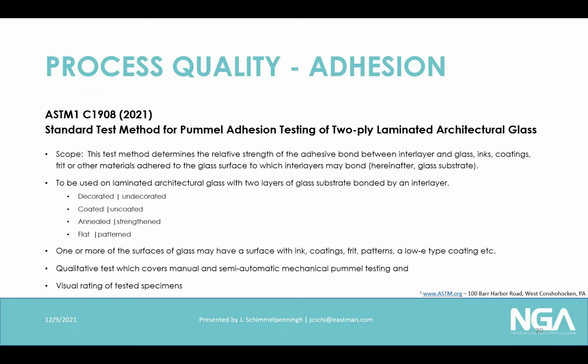Okay. So the big change in the last few minutes is the adhesion test. This is the Pummel adhesion test. Now the Pummel test has been around in the industry for decades. And this is a method to look at the relative strength of the adhesive bond between the interlayer and the glass, or inks in the glass or whatever. It is a method that is destructive. It can't be run in place. It has to be done in a laboratory. And again, it is a destructive method.